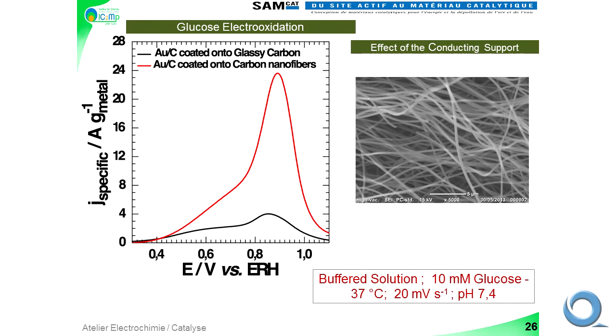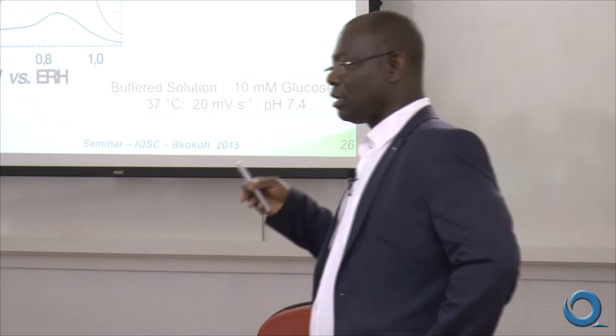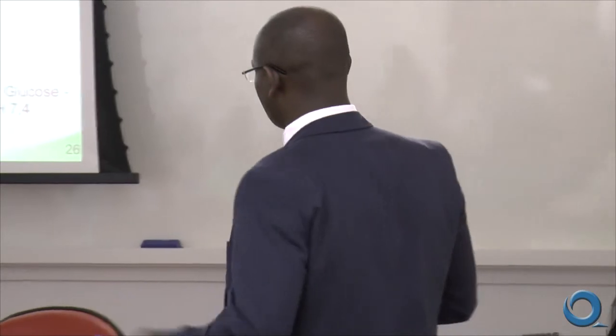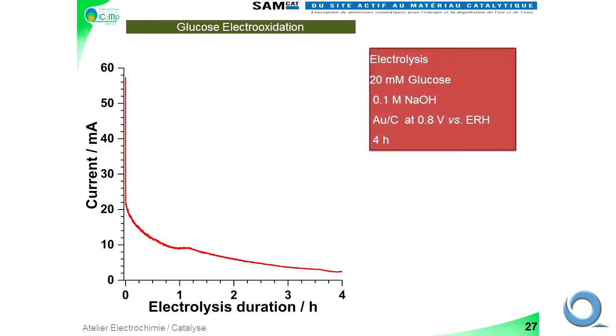With glucose, we would like to change the graphitic carbon, because of hybridization sp2, sp3, for example, graphitic is not interesting when you apply a high potential. For example, you can oxidize graphitic carbon to CO2. So we use carbon nanofiber. And as you can see, we increase the current density by changing only the supporting conductor. This is very, very high. And during 4 hours, we carry out electrolysis at the surface of this catalyst.